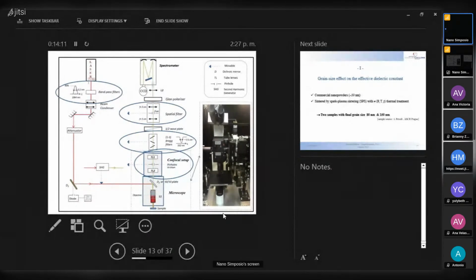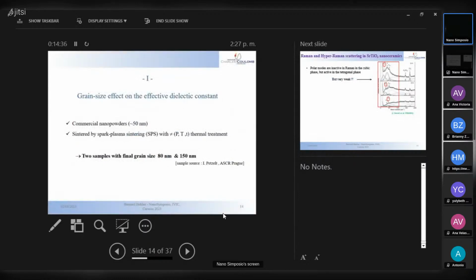And then you irradiate your sample with an IR beam, infrared beam, and you look at the scattered beam in the green. Okay, there are different setups here, but after, this arm here is similar to Raman, somehow. Okay, so for this study, we had at our disposal one commercial nanopowder of 50 nanometers, and this nanopowder was sintered by plasma sintering, and we got two samples with grains of 80 nanometers and 150 nanometers. So we have two samples at our disposal to do our study.